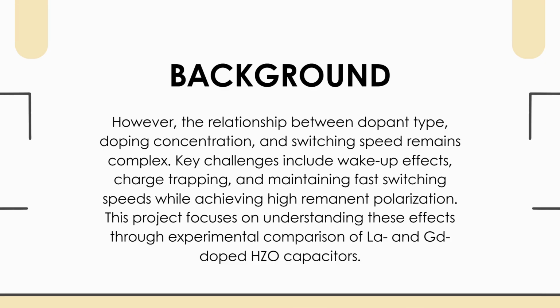And to make hafnium zirconium oxide ferroelectric, we often add dopants like lanthanum or gadolinium, but how we add them and how much can change how well the material works, especially how fast it switches and how much charge it can hold. So in this project, I wanted to study how lanthanum doped and gadolinium doped hafnium zirconium oxide behave and which one works best.